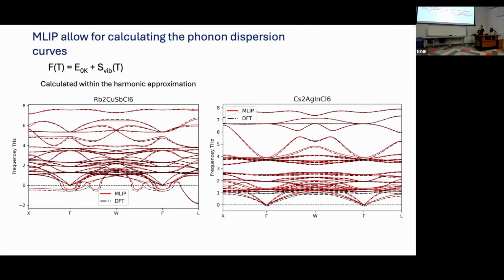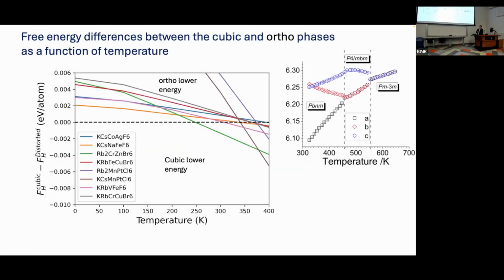And that's a very difficult calculation with DFT because it requires calculating vibrations at many different k points. But with the MLIP, we get forces, we train it to forces, so it should be accurate in calculating the vibrations. And that's what you see here, where you get similar phonon bands. So the overlap between the red line and the black line implies that the model's pretty accurate in calculating phonons, which means that we can accurately calculate the free energy. And what was interesting, on the one on the left, you could see that there are actually imaginary frequencies in the structure, implying that it's going to relax to something lower in energy. So it's not stable in the cubic. These are both performed in the cubic phase.